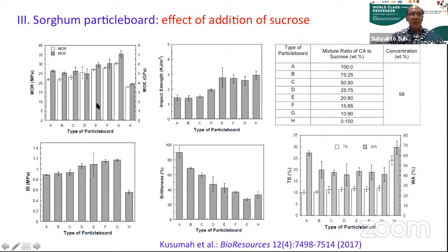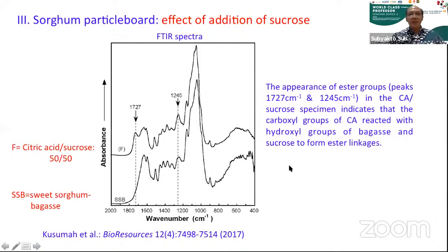And these are the mechanical properties. We can see here that G, which means the ratio of citric acid to sucrose of 10 to 90, has the highest properties, also the internal bond strength. And here we can see the brittleness decreasing with increasing sucrose. And we get the smallest brittleness in this G. We checked this with FTIR spectra, and we can see here, similar to the previous work, that ester linkages are formed here.